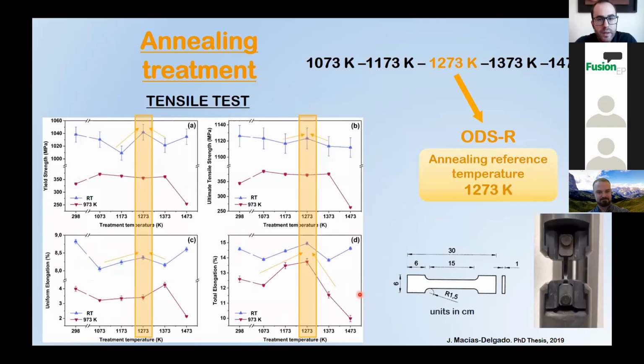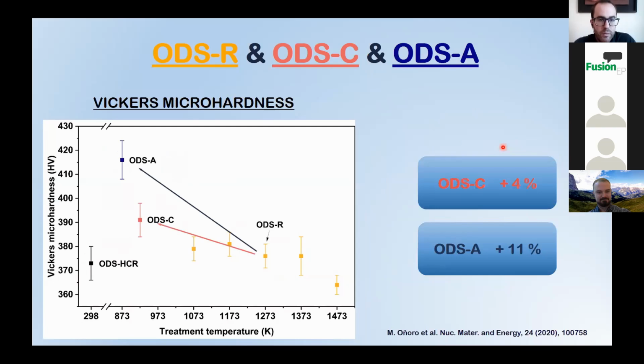Tensile test experiments performed at room temperature and 973 Kelvin are represented as a function of the annealing treatments. This allowed us to highlight the 1273 Kelvin as the optimal annealing treatment. These samples were named ODSR and used as reference for comparison. Now, from the ODSR sample result, we completed the Vickers microhardness investigation. We observed a hardness increase for both the cycled and the aged samples, named ODSC and ODSA respectively. This increase was more evident for the aged material.